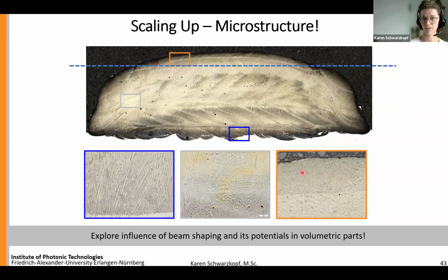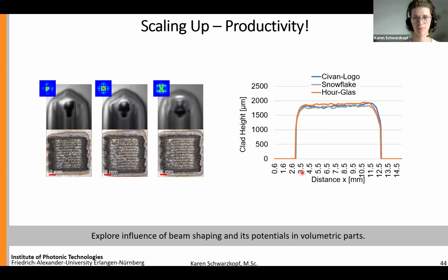Next to microstructural adjustments in volumetric build-ups, it's also the increase of productivity that can come with different beam shapes. First insights have been generated here, for instance, with a Civan logo beam shape, a snowflake, and an hourglass, which basically steers the melt pool like this. And we could already see a slight increase of our clad height when employing such a steering of the melt pool.